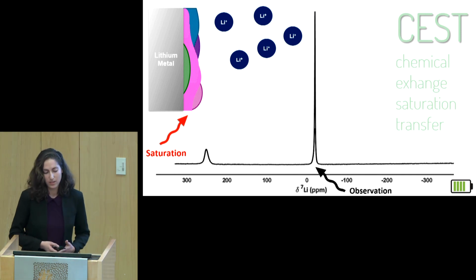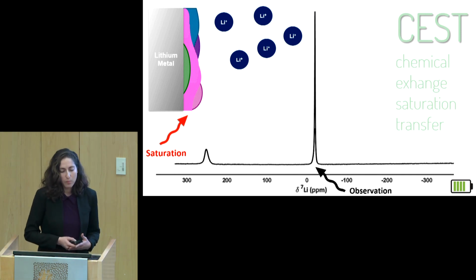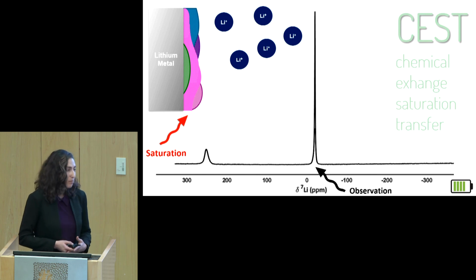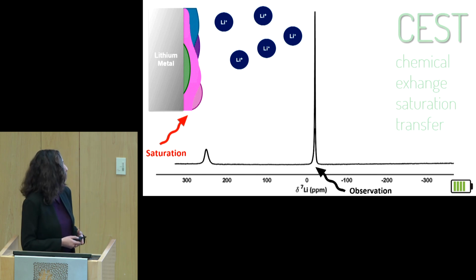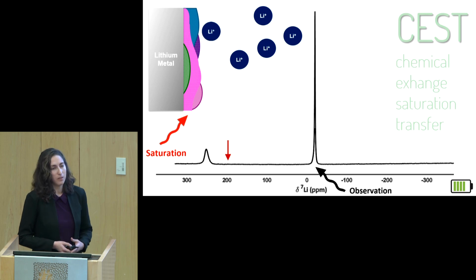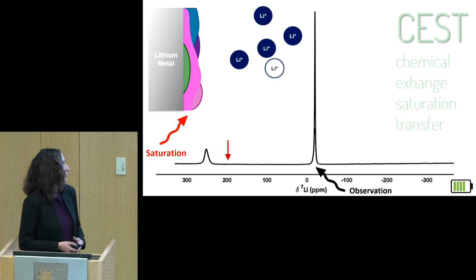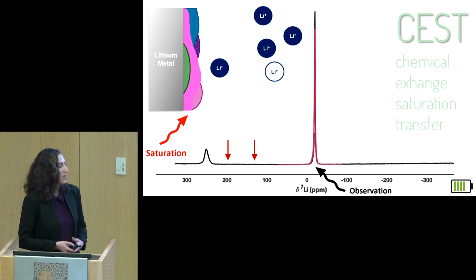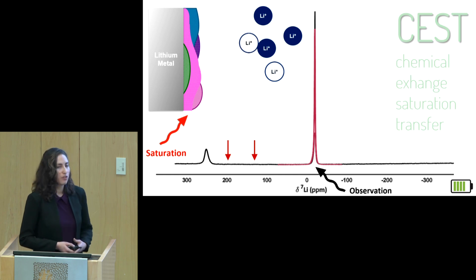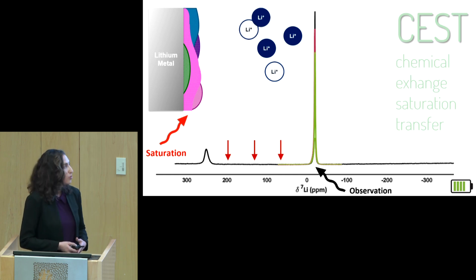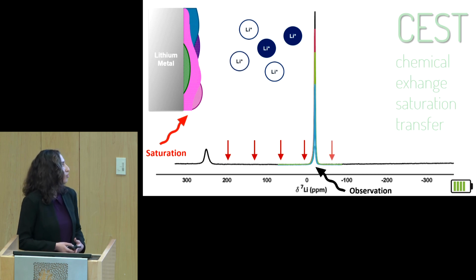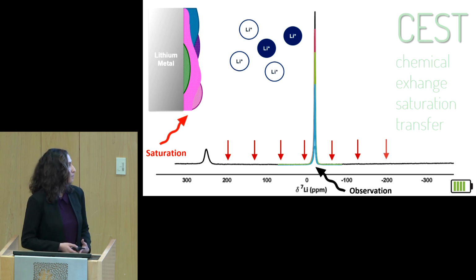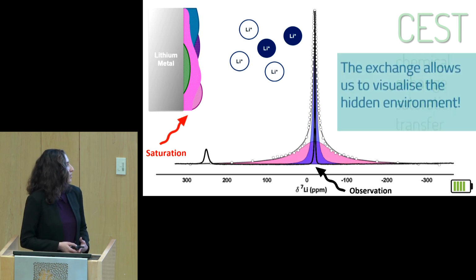So this is what I tried to achieve. By applying pulses at frequencies I suspect belong to the surface-bound lithium, I can kill their signal, basically making them invisible to the NMR measurement. So when the lithium ions detach from the surface and return to the solution, they reduce the intensity of the signal of the dissolved lithium ion. And as I get closer and closer to the peak of the dissolved lithium, the reduction will be greater and greater. By quantifying this reduction, I can finally see the elusive surface layer.